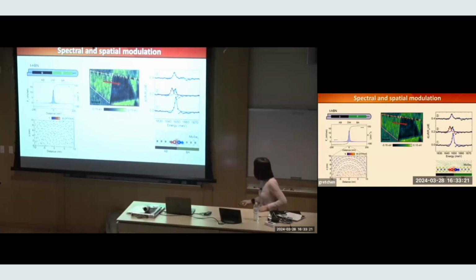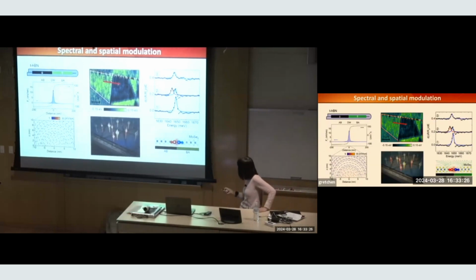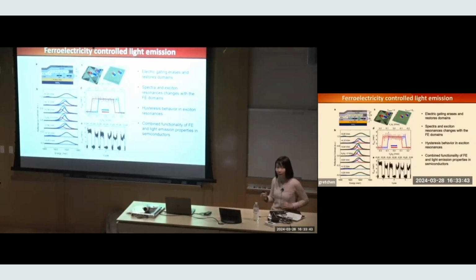So what it really does is the hBN is modulating both the pattern of emission and the spectrum of the emission periodically. So it follows the period of the Moiré supercell created by the hBN. I don't want to elaborate on the details, but I also want to show you I can combine the ferroelectricity with